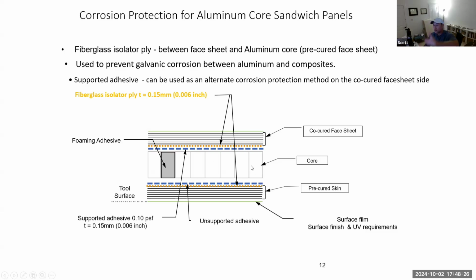So here's a cross-sectional view of the various components that make up the honeycomb core sandwich panel. If you start from the bottom up, we have a surface film, which is this green. These blacks are the pre-cured skin laminate. The orange is the fiberglass isolator ply, which is meant to be that barrier between the carbon fiber and the aluminum core. You have the adhesive to bond the face sheet to the core. You have the core itself, and then you have foaming adhesive to bond the cores together, because it's not just one big gigantic core, it's modularized cores. It's cores that are different shapes that you have to put together, so you have to kind of glue them together. And so the foaming adhesive is the way you can glue cores together. And then the other side is the same thing. You have supported adhesive, fiberglass isolator ply, and the other side of the face sheet, the co-cure side of the face sheet.